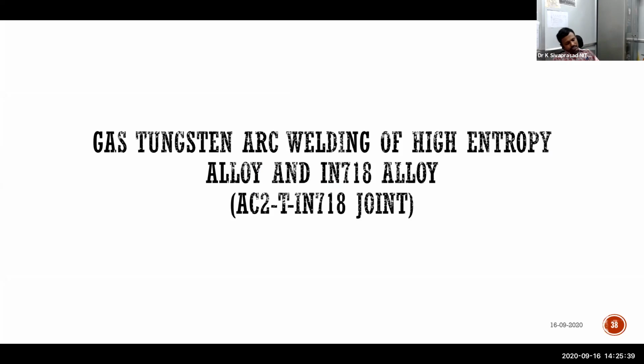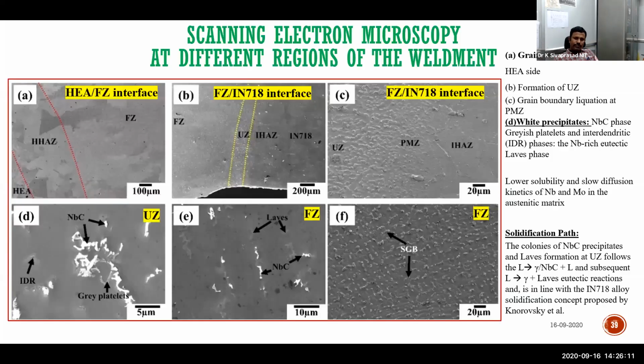Why do we want to take Inconel 718 on one side and austenitic stainless steel on the other side to weld along with HEA? On one side, austenitic stainless steel, less nickel will be there, 18% chromium, 8% only nickel. Compared to that, 20% nickel in the high entropy alloy. And in the other system we have taken Inconel 718, where nickel will be 52%, whereas high entropy alloy 20%. So to see these transitional joint variations also, we have chosen these systems. We have seen again the unmixed zone here, where no doubt a good amount of BCC has formed.